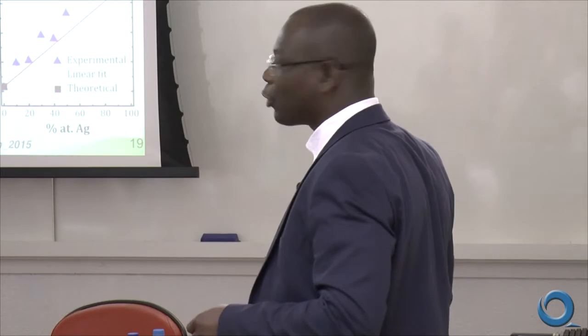Conversely, when you have, for example, silver, which is larger than palladium, we see that when we increase the silver content, we increase the lattice parameter.